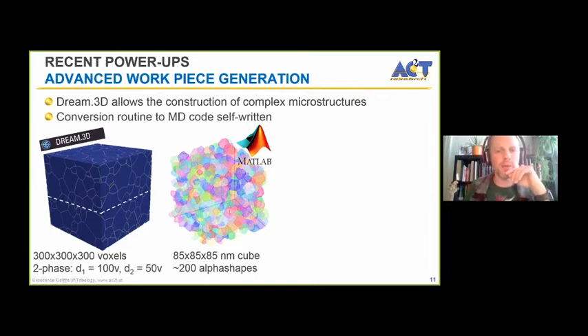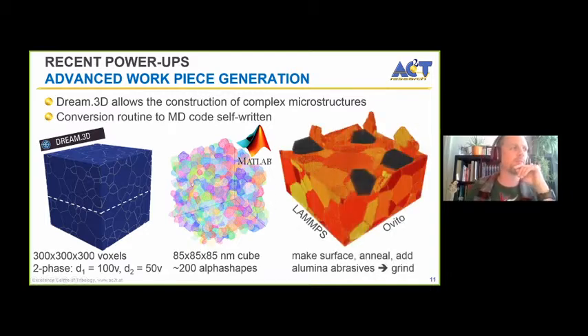And then I had to program my own conversion routine that basically reads this structure and makes it into something that my MD code can read. So basically, I make this into alpha shapes. I fill the alpha shapes with the lattice that I want to put in there. And this already gives me the orientation. So this already makes sure that there are not too many low angle grain boundaries and so on. And then I just cleave somewhere where I want to have the surface. I anneal it to make sure that it's in thermodynamic equilibrium. And then I add some alumina abrasives on top and I start grinding. And this is pretty much the point where we are at with the grinding simulations. So this is already the large system, 25 million atoms.